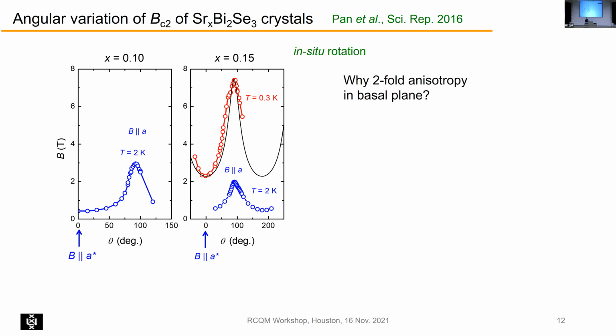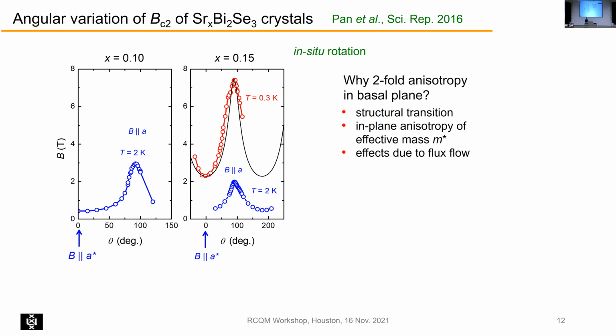Now there can be, of course, a number of maybe ordinary reasons. You could have a structural transition. So we checked that. This crystal stays the same. It's trigonal down to low temperatures. You could have an in-plane anisotropy of the effective mass, because the upper critical field is related to the coherence length, which is related to the effective mass. But this effect is very large in the upper critical field. And there are quantum oscillation data on bismuth selenium 3 with the field changing in the plane, and the anisotropy of the effective mass is really very small. So it cannot be due to anisotropic effective mass.